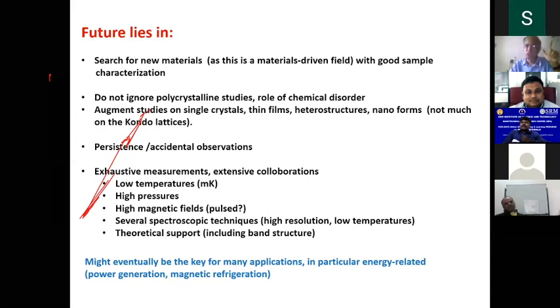You do have a strong anisotropy in all physical properties. So you also have anisotropic hybridization. If you measure on a single crystal, the Kondo temperature, which measures the hybridization, can be direction dependent. Therefore you have anisotropic hybridization depending upon the orientation of the 4f orbital. This is established.